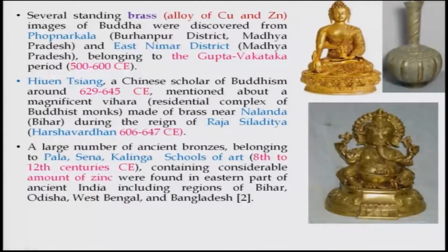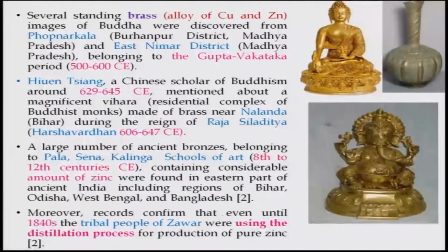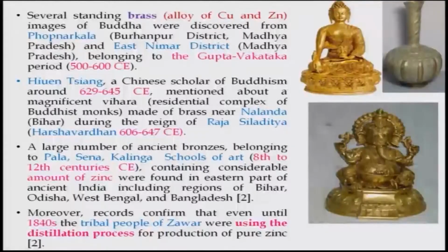A large number of ancient bronzes belonging to the Pala, Sena and Kalinga schools of art, around 800 to 1200 CE, contain a considerable amount of zinc, and were found in the eastern part of ancient India, including the regions of Bihar, Odisha, West Bengal and Bangladesh. And moreover, records confirm that even until 1840, the tribal people of Zawar were using the distillation process for production of pure zinc, and that clearly indicates that the British might have learned about the distillation process of zinc smelting from the tribal people of the Zawar region.